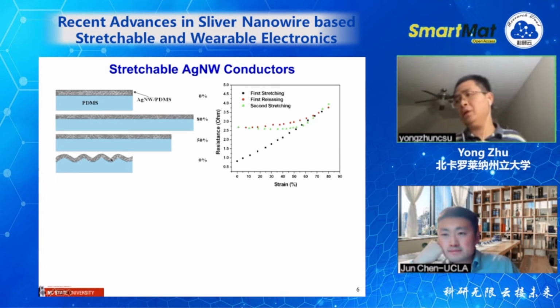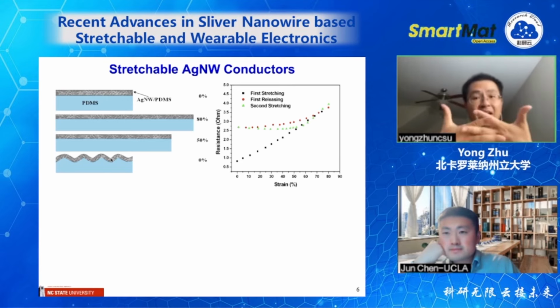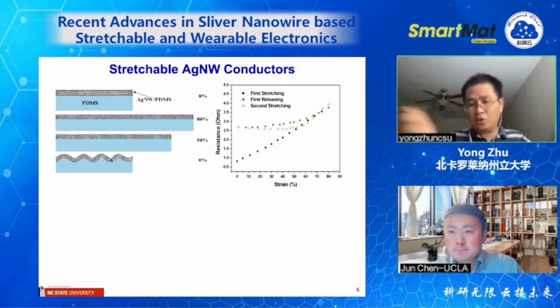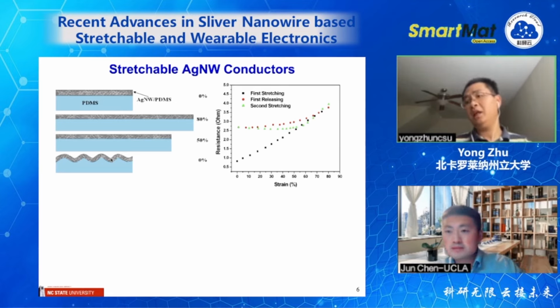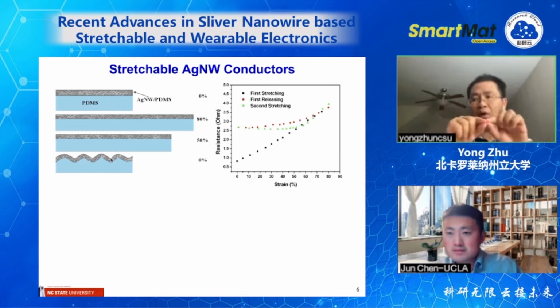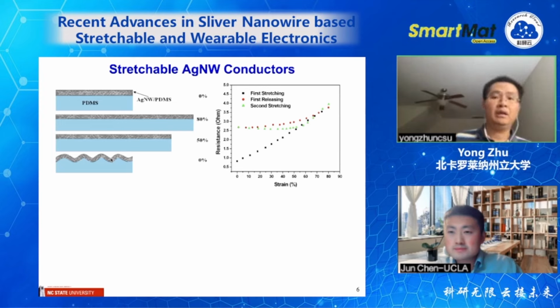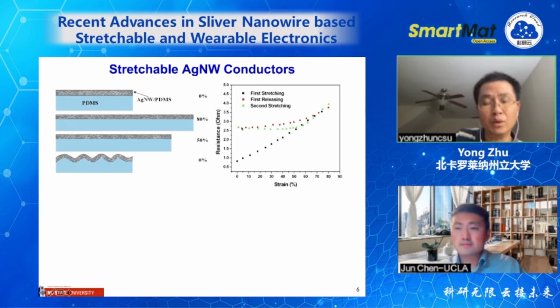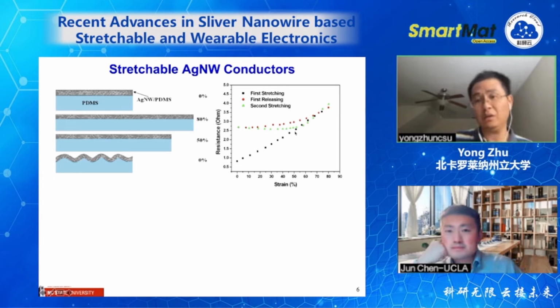The wrinkles here. But what happens is when you stretch and the sliding happens, the wire itself also gets stretched, and it depends on how strong the bonding is between the nanowire and the matrix. If the bonding is very strong, we can break the nanowires, maybe before the sliding happens. Actually, we found those, because we tried to understand them. If the bonding is very strong, that can happen. If the nanowires break, the behavior will be very different. When they release, the resistance will probably increase much more than what we observe here, and it may not be constant anymore.